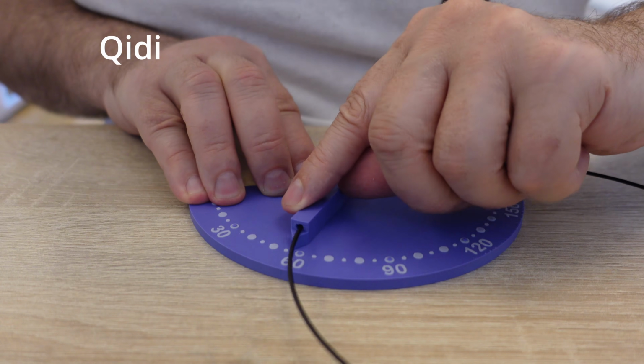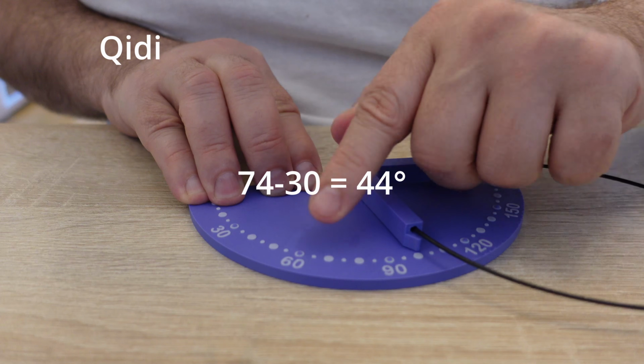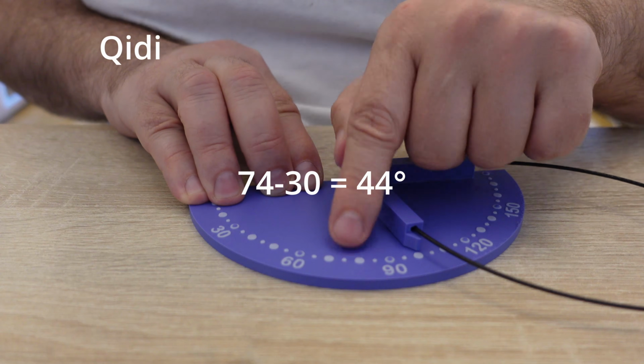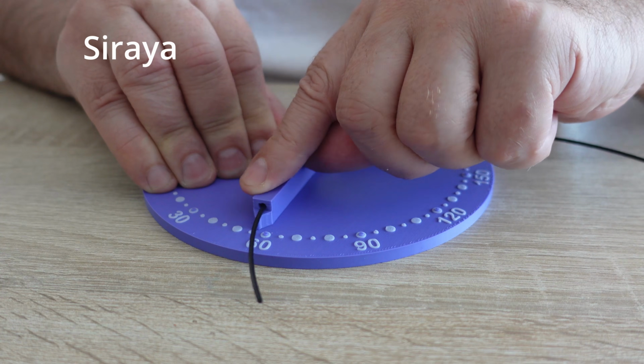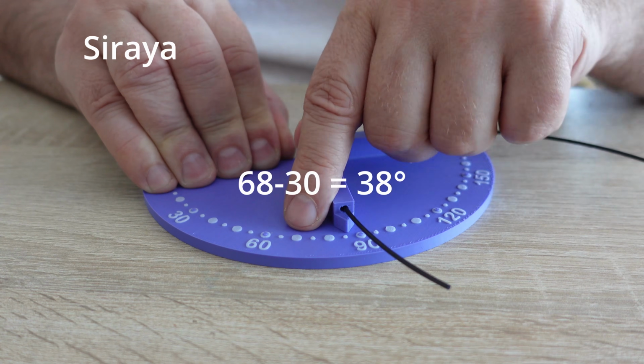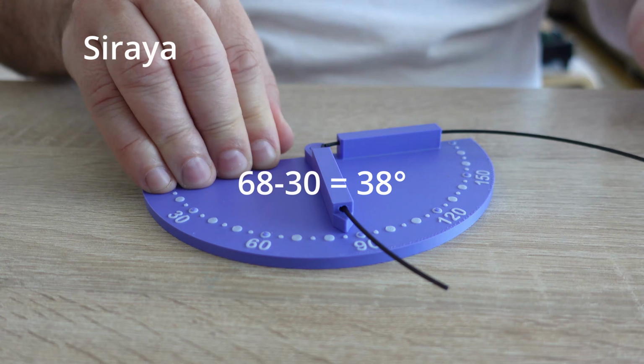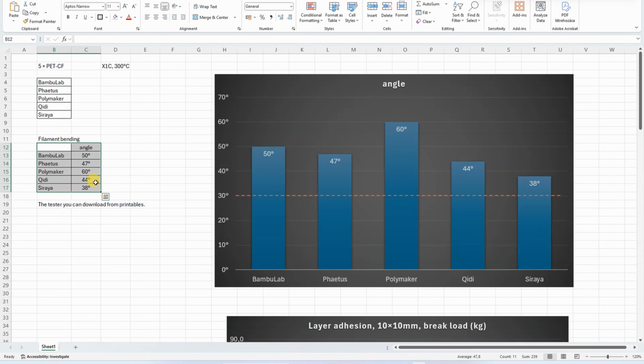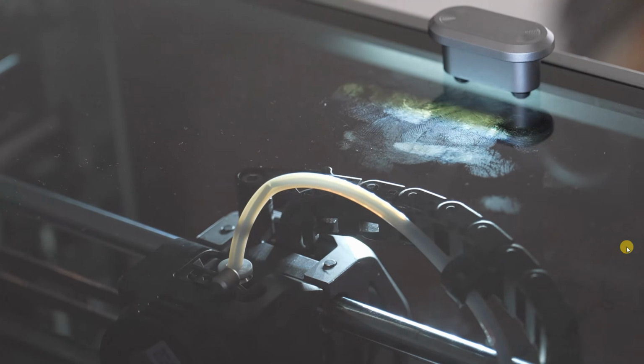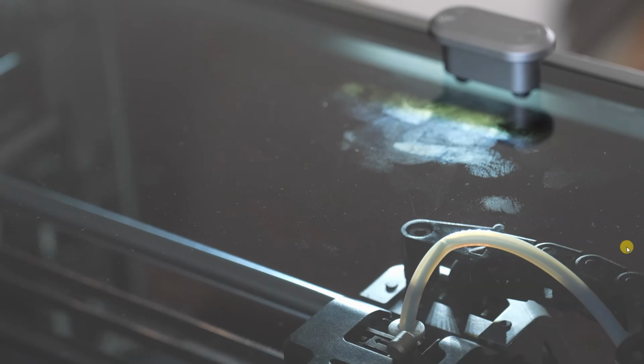Qidi Tech. 74. And Siraya. The most brittle filament. Around 70, but I will check the footage. I'm not sure how important this data is. For me it's enough that in all 5 cases they are above 30 degrees, because I noticed that below this value it's too brittle and it may break in some Teflon tubes if bent too much.